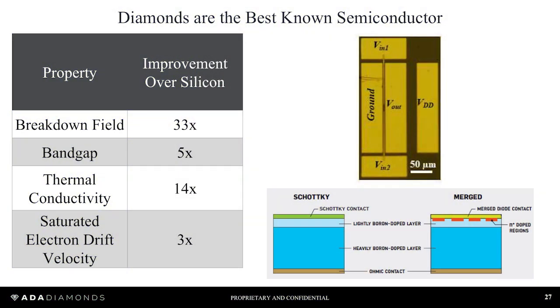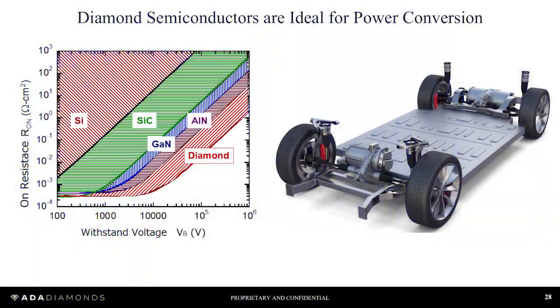So to give you a few examples, this is a MOSFET logic circuit on a hydrogen-doped diamond. That has successfully run at 300 degrees Celsius and 2,000 volts of electricity. The diodes below have run up to 1,000 degrees Celsius and in theory can support well over 10,000 volts of electricity. That's important because these two basic units of computers are all that you need to fulfill the most important application of diamond in the future, which is power conversion.